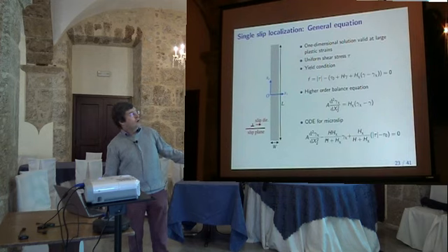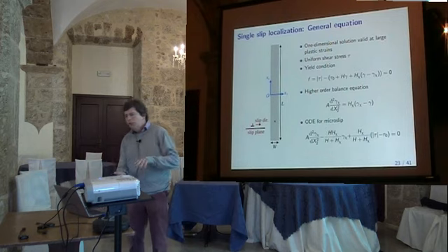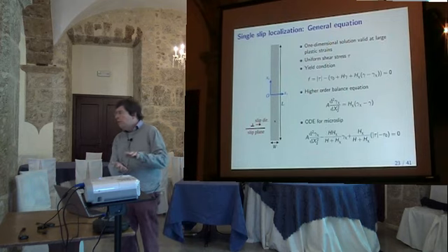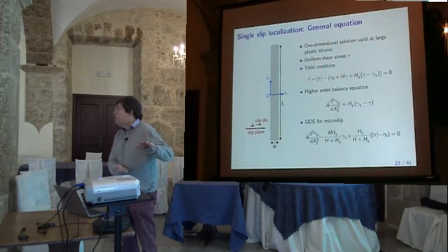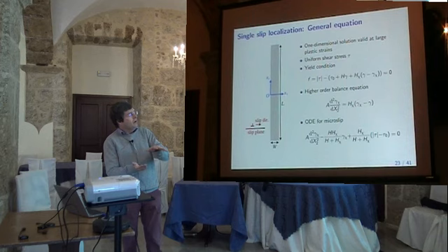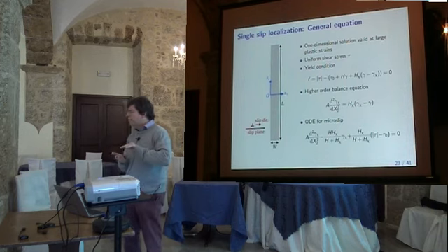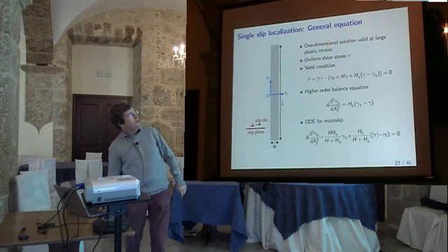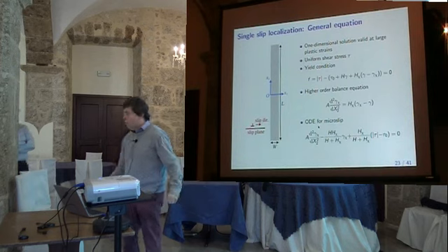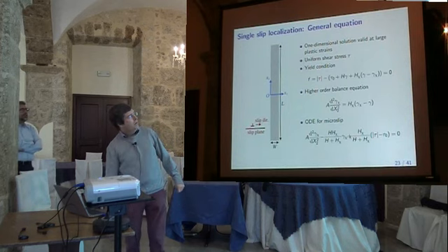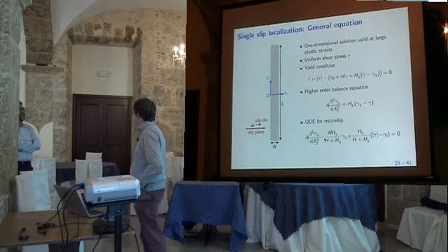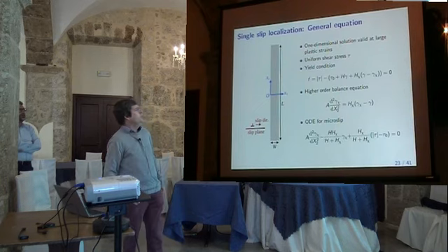What else can we solve? I have to say that due to a balance of stresses, you have uniform shear stress in this case, of course. So we have to take this into account, homogeneous shear, and then you take into account the fact that we have yielding, so this is 0 here. Then we find an ordinary differential equation for the microslip here. This is a second order higher order balance equation. Where do you see that?